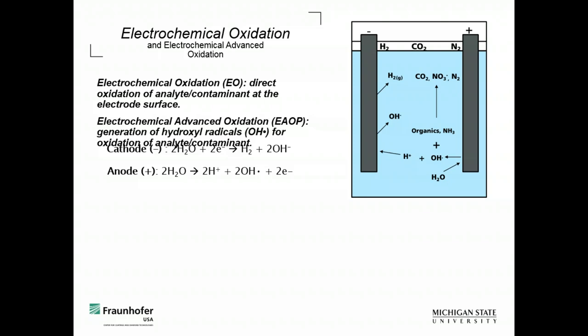But an organic, this is real common for traditional wastewater treatment, an organic will interact with the electrode surface, whether that's direct electron transfer at the electrode surface, or we can generate hydroxyl radicals at the anode surface, and that can scavenge an organic contaminant, and then effectively oxidize it or mineralize it into its components, which is CO2 and water. In the case of PFAS, we get CO2, water, and fluoride ions. But nonetheless, that's an advantage of this technology, that it is destructive.